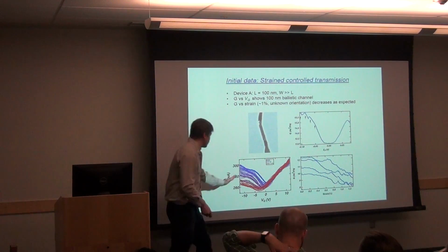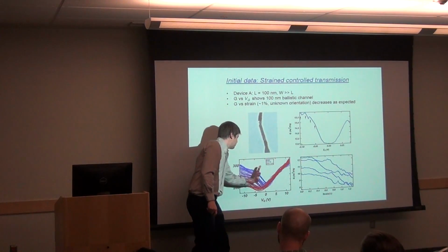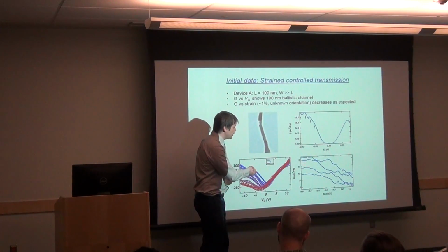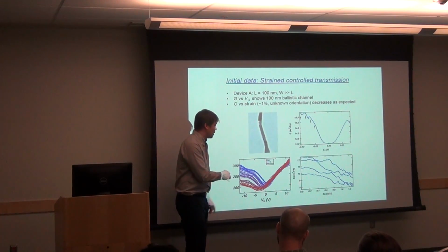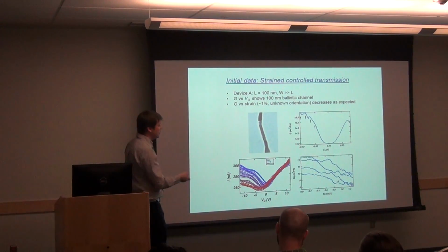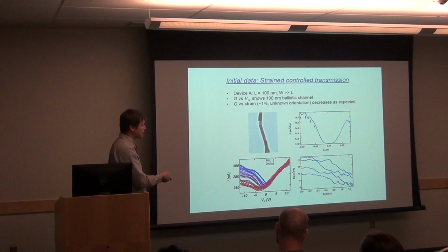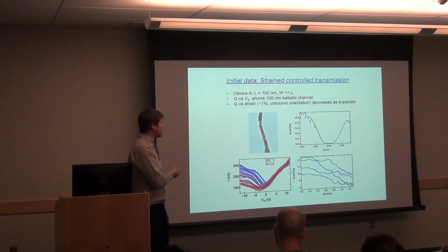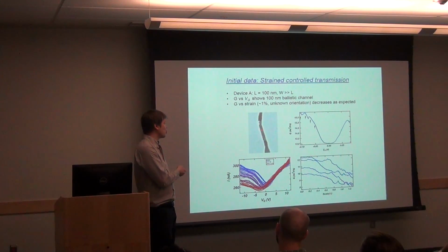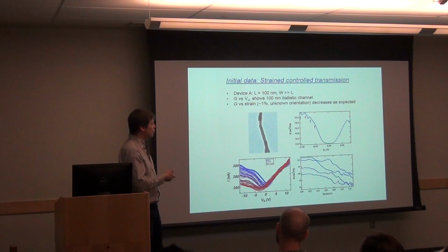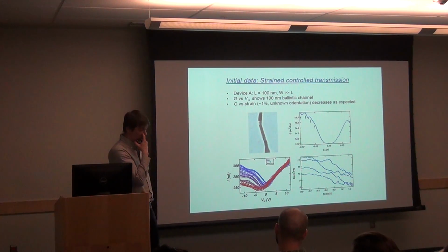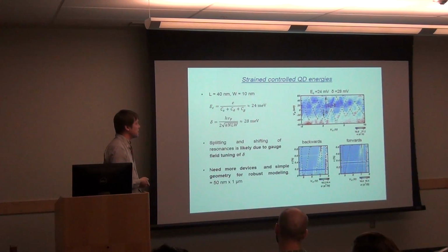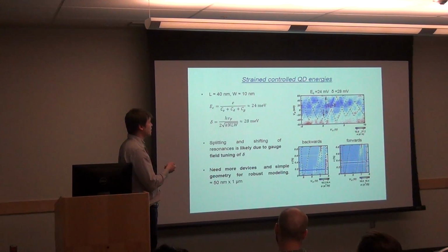And those curves are just basically extracted into the lines, but at different gate voltages. So at all gate voltages, you can see that the conductance goes down. And definitely, because the range of strain is small, there's some noise, but there's a factor of 40% decrease or something in conductance. So we think that we can basically, by going to these shorter devices and building a few more devices so we have different crystal orientation, demonstrate that we can turn off this current and build a quantum strain transistor. We also saw similar effects on quantum dots.